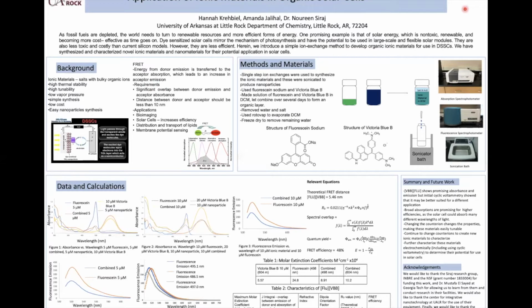So we wanted to make a novel dye pair that could be used for a dye-sensitized solar cell. We used a single-step ion exchange method where we combined our donor material here, fluorescein sodium, with our acceptor material, Victoria Blue B. We dissolved each in their respective solvents, allowed them to stir over 48 hours and combine. Then we are able to remove the counter ions, which have formed a salt in the water layer. We're left with our ionic material in dichloromethane, which we can rotovap to evaporate the DCM and then freeze dry to remove water. Then we're left with our material to characterize.